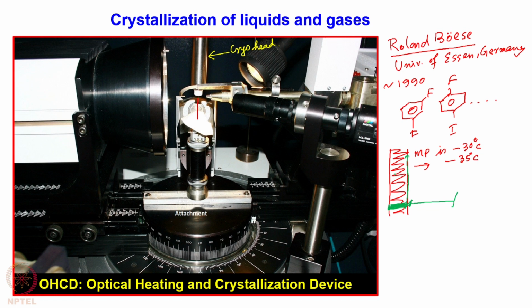And then if somebody moves this molten zone upwards by moving the mirror slowly, by moving the laser upwards, the molten zone moves up and the lower zone again recrystallizes, and this process is done several times. And if suppose the length of this capillary is about 3 centimeter, the laser beam travels this 3 centimeter distance in 2 to 6 hours.